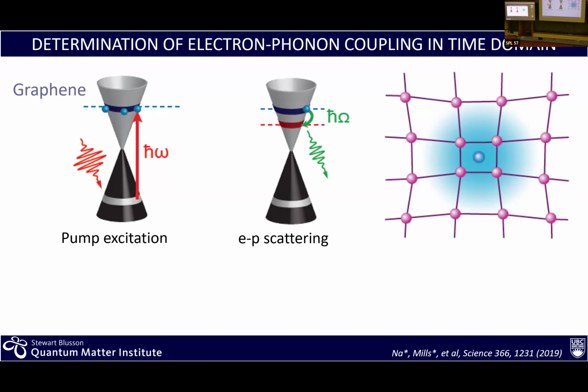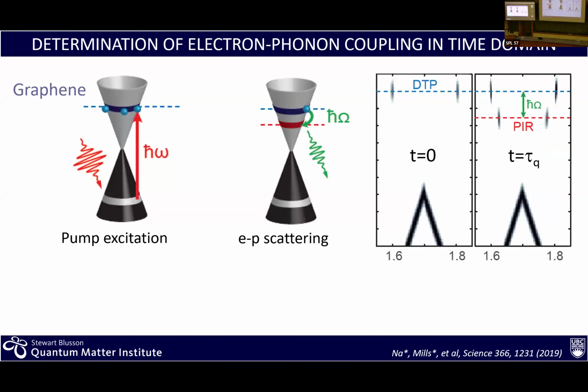And so we know that over time, this electron will also scatter, emitting a phonon and basically dropping down to an energy corresponding to the phonon energy. So here is what an experiment would look like if you did it time resolved. At t equals 0, let's say pump and probe are superimposed. You're going to photoemit from the occupied part of the cone, but you're also going to see intensity up there, where you have excited them optically, right here. But if you wait some time, the characteristic scattering time for electron-phonon scattering, well, then you're going to see some of the intensity trickling down exactly by the frequency of the phonon.